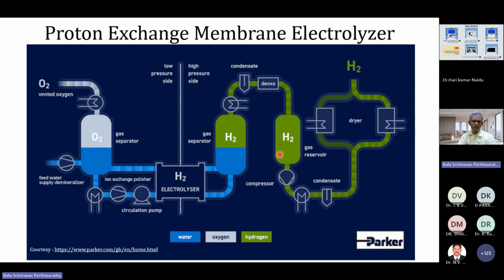So this is how the industrial level system would look like. When I say industrial level, we are talking about production rates of the order of a few hundred tons of hydrogen per day, using megawatt kind of electrolyzer capacities. So the stacks will have a low pressure, high pressure side. Electrolyte will flow through. In this case, it is the high pure ASTM water, as they call type 1 water, with the absolutely controlled conductivity levels. The millisiemens per centimeter, microsiemens per centimeter numbers specified for the application need to be met. You must use the right kind of membrane. It is a kind of a stack.